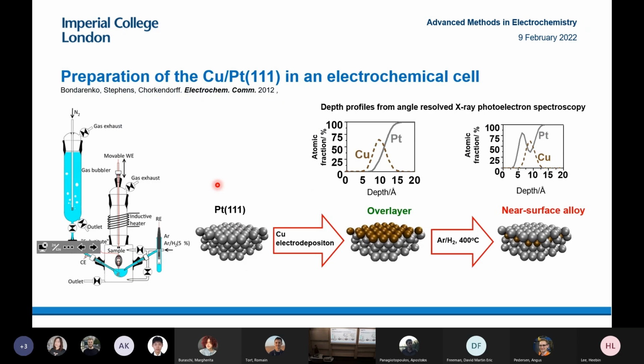And we actually decided, okay, obviously it's quite difficult to transfer samples from an ultra-high vacuum chamber to electrochemical cells. So we thought, how can we do this in a less cumbersome way? Can we make this near-surface alloy using the methods we have in the electrochemistry lab? So we built a special cell, where we use what's called underpotential deposition of copper onto platinum, where we just deposit around one layer of copper. Then, in the headspace above the electrolyte, we'd anneal the platinum single crystal in hydrogen.